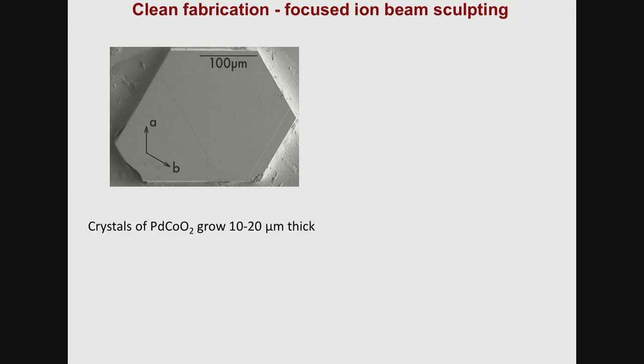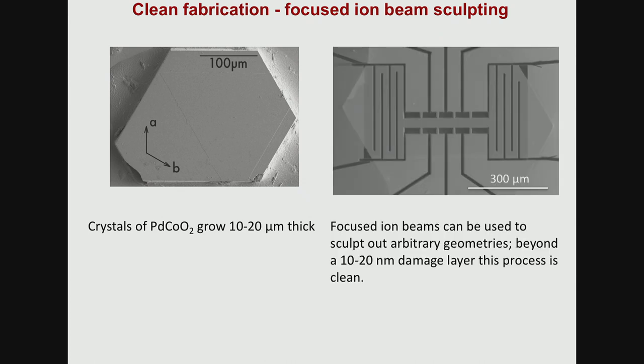The other experimental development to tell you about, which is relatively recent, is that the other thing you need to do hydrodynamic or ballistic experiments is the ability to make mesoscopic devices from the materials of interest. For a long time, you could only do that reliably with semiconductor 2DEGs. Then graphene came along and great techniques were developed for doing that. Now people are showing that focused ion beam sculpting is a way of taking as-grown single crystals of almost anything and making exactly the device geometry that you want from them.